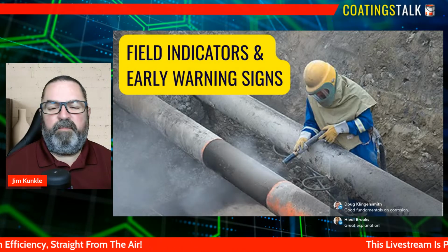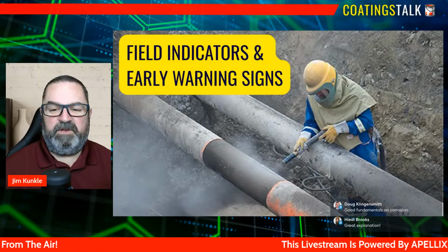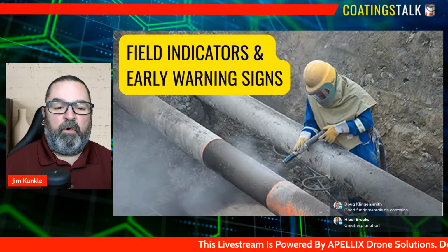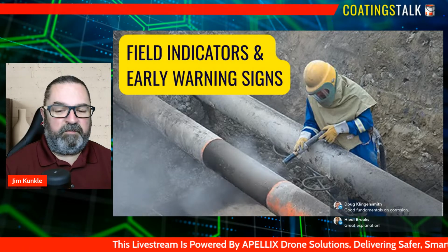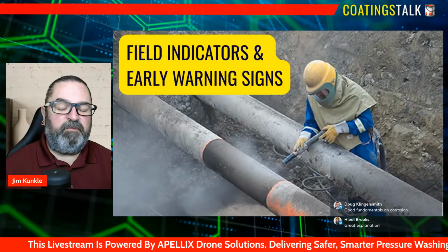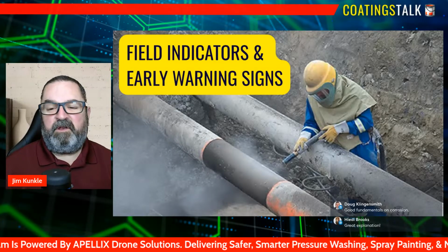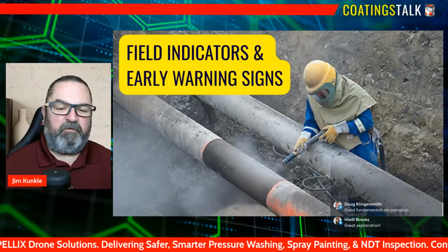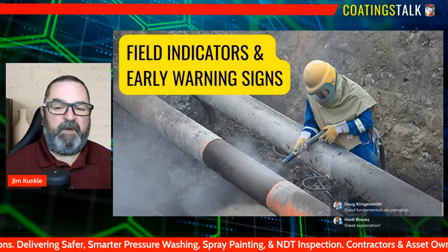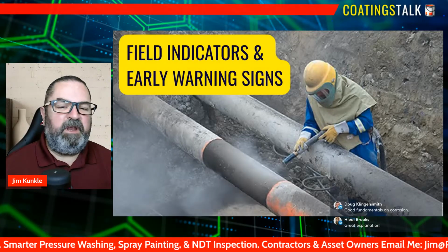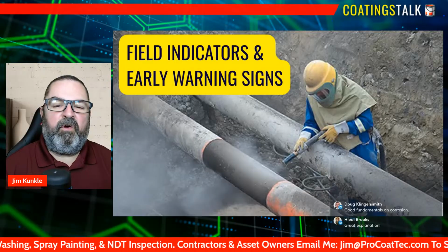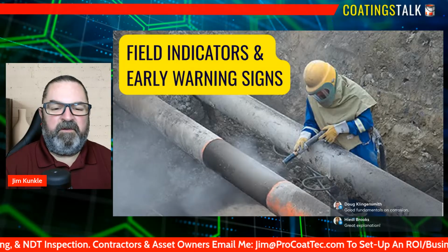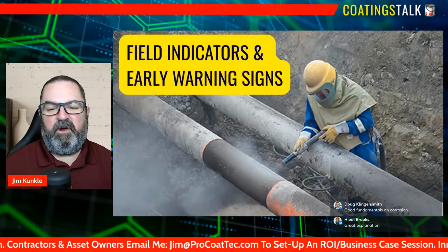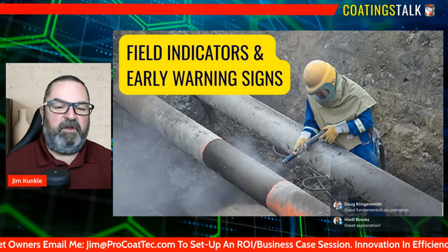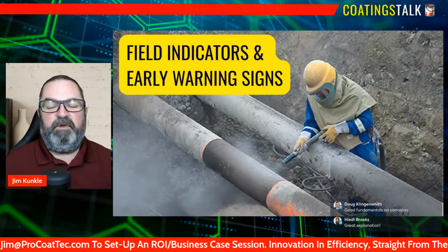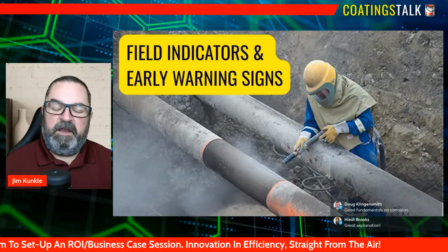Applicators should also be alert to improper surface preparation, inconsistent film thickness, or overspray that leaves thin, vulnerable spots. These application-related issues may not show immediate corrosion, but they set the stage for premature failures once the asset's back in service. And by training the eye to recognize these early indicators, field teams can intervene before corrosion becomes severe. This proactive mindset not only protects the asset, but it also reduces long-term maintenance costs and enhances safety